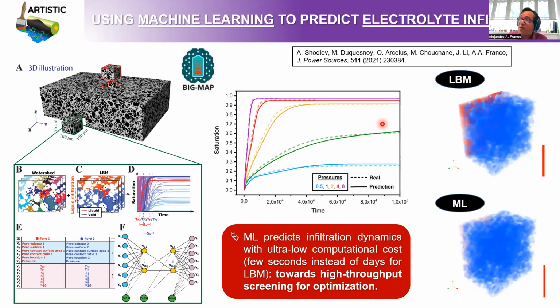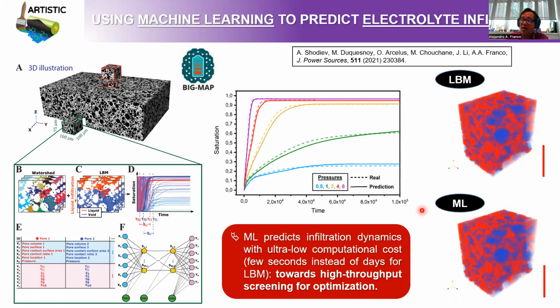So here is what we have performed in this work that we published last year. We have derived, from the data coming from these LBM simulations of electrolyte infiltration, a machine learning model that is able to predict the saturation curves. That means the amount of liquid per unit of volume of pore in your electrode microstructure as a function of time, for different pressures applied during this infiltration process. This machine learning model is also able to reproduce very nicely the trajectory of the liquid electrolyte in the pore network inside the electrode.